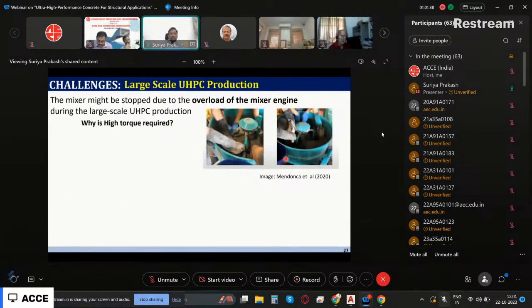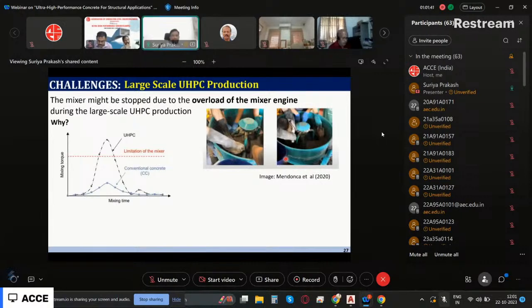Okay. Now, there is the mixer, sometimes when you are using a normal mixer. In fact, for UHPC, to ensure proper performance, what we use is a twin shaft mixer, which is a specially designed, high-speed shear mixer. You cannot use a regular drum mixer or pan mixer. We can use it, but if you're using a regular pan mixer or drum mixer, then your mixing time will become more. Then you can overload the mixer engine. Okay, so this is the limitation.